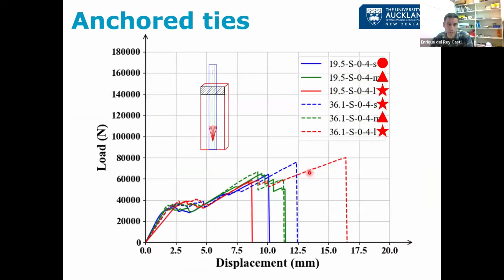And this is not just one test. We have seen this repeated over many, many tests. This is 2 concrete strengths, 20 and 36 MPa, different anchor sizes. So the behavior is very repeatable. We have elastic, debonding, anchor. We can calculate those two.